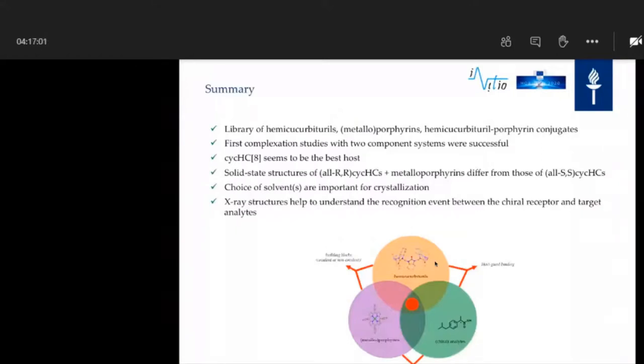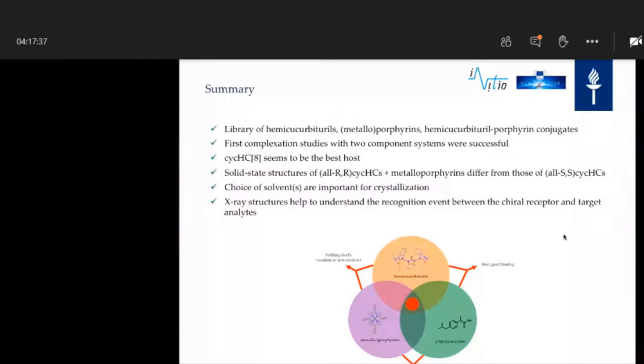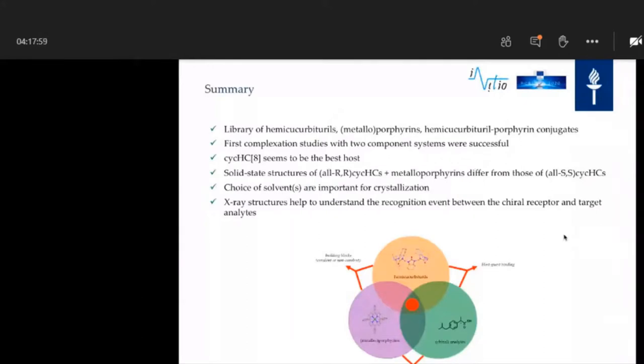It seems that the eight-membered macrocycle is the best choice to have some kind of interaction inside the cavity — the six-membered ring is too small. We have seen there could be some differences between the solid-state structures of the all-RR and all-SS. The choice of solvents is very important. These X-ray structures can help us understand the different binding modes between the receptor and analytes — even though we will not do it in the solid state, but most likely in solution or gas phase.